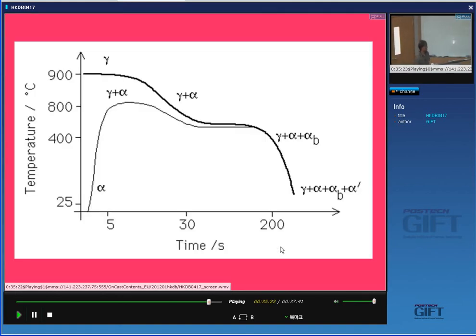And you can produce this in two ways. Okay, the common way is you start with a fully austenitic sample, you generate about 70% of allotriomorphic ferrite at high temperatures, and then you transform it into bainite at around 400 degrees centigrade, which is roughly also the temperature at which you might galvanize the material. Okay. Alternatively, you can start with a cold rolled steel and heat it up into an intercritical zone where austenite and ferrite can coexist. So you have your annealed ferrite, and then you've generated retained austenite, and then transform it here into bainite. And this process itself takes a few minutes.